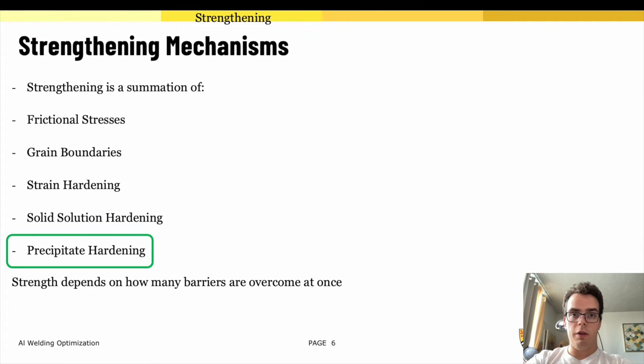We discussed earlier that aluminum is starting to rival steel in strength. How does this come about? Well, strengthening is a summation of multiple factors happening at concurrent stages. While we'd like to apply all these at once to get the maximum critical strength, we will see they'll be activated at different times. But in general we see frictional stresses just due to the friction between atoms. We see the grain boundaries of polycrystalline materials, so essentially how each subset of atoms stacks up together with misorientation angles. We see strain hardening. Some of you may have been familiar with cold working.